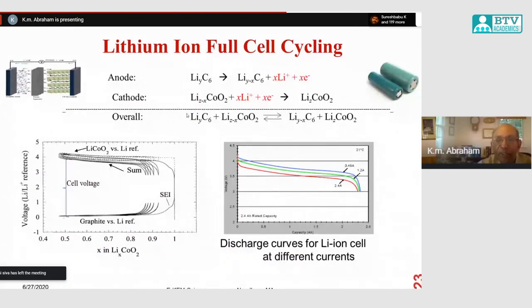All right, so now finally we come to a full battery. You have the anode and the cathode. You put together the graphite and the cobalt oxide in this case, and the voltage you are measuring is simply the difference between the voltages of the two. This is the fully charged battery, so it's around 4 volt, and then when you discharge the battery, the voltage comes down, and you stop it around 3 volt, because below that there is no capacity.